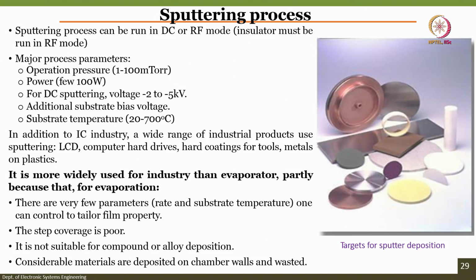Then what is the second thing? The major process parameters are, one, operation pressure of 1 to 100 millitorr. Second, the power, which is a few hundred watts. We can also change the power in sputtering from 100 to 200 to 300 watts, and depending on the power, the rate of deposition would change. As I told earlier, if you increase the power, the rate of deposition increases. If you increase the distance between source and target, the rate of deposition decreases. If you decrease the power, the rate of deposition decreases. If you decrease the distance between source and target, the rate of deposition increases.